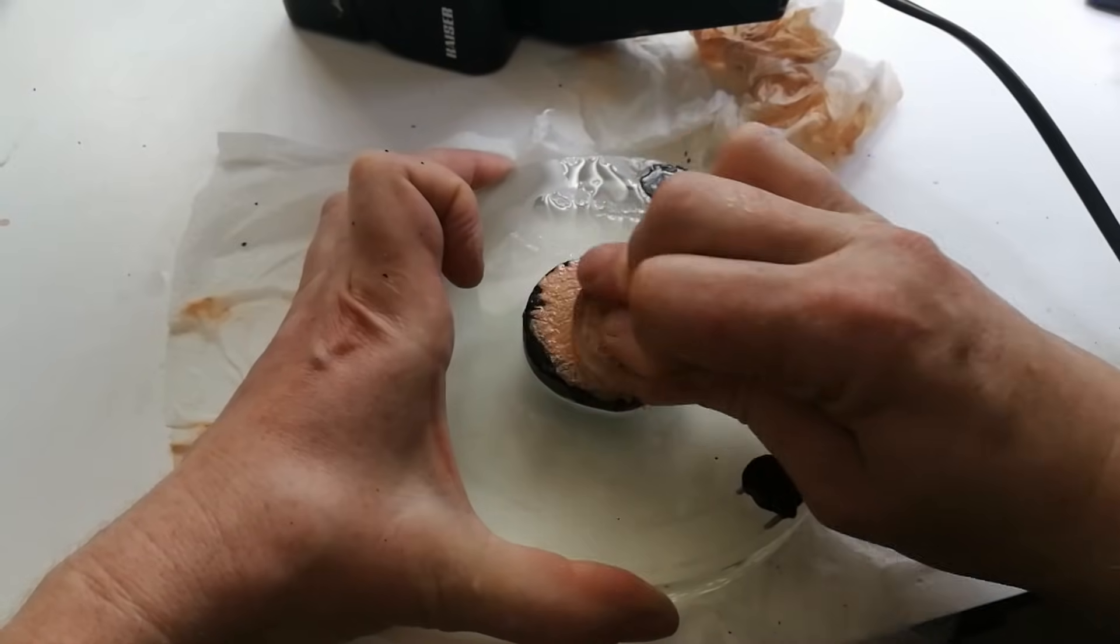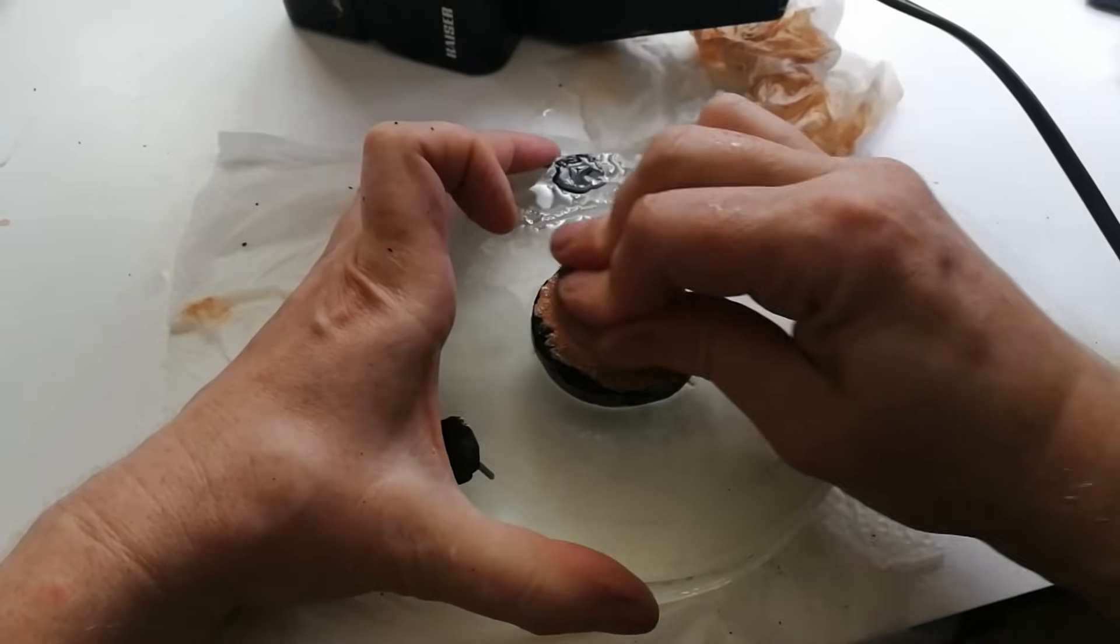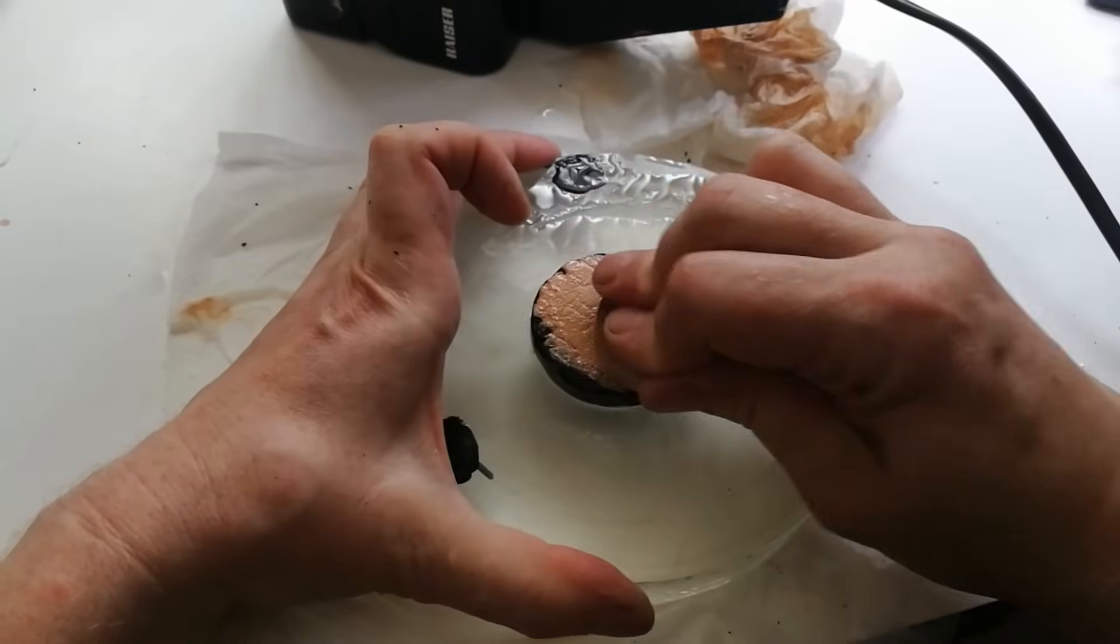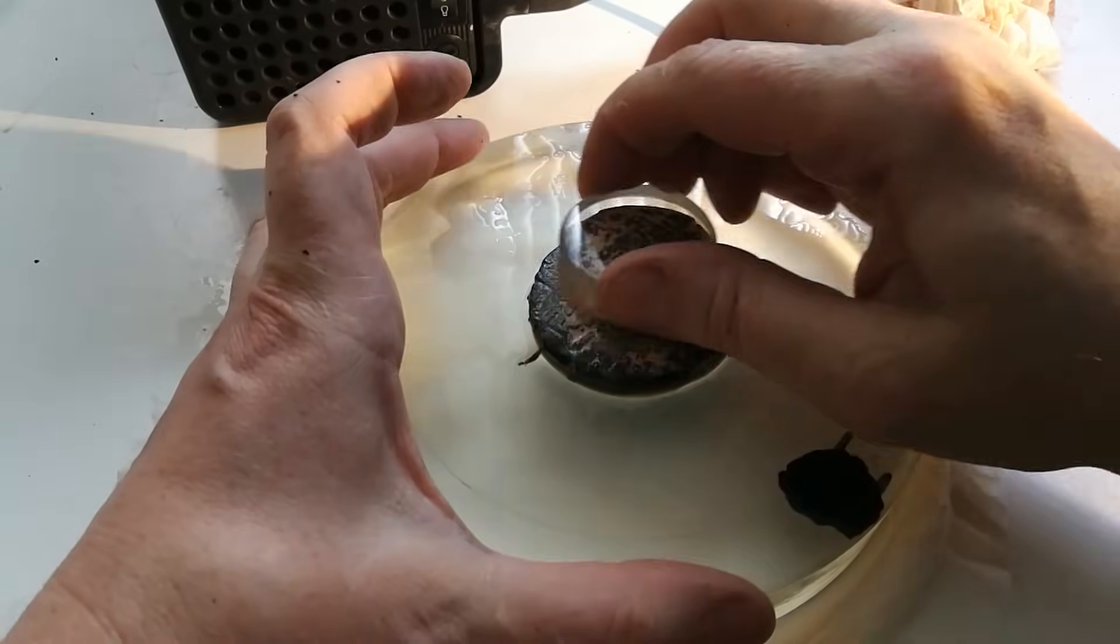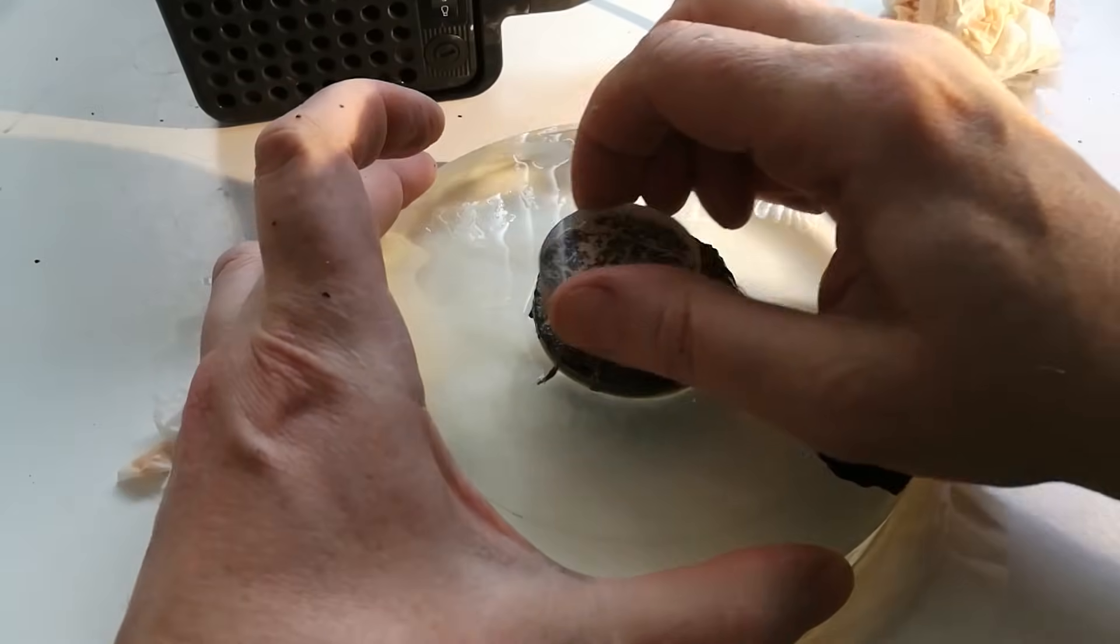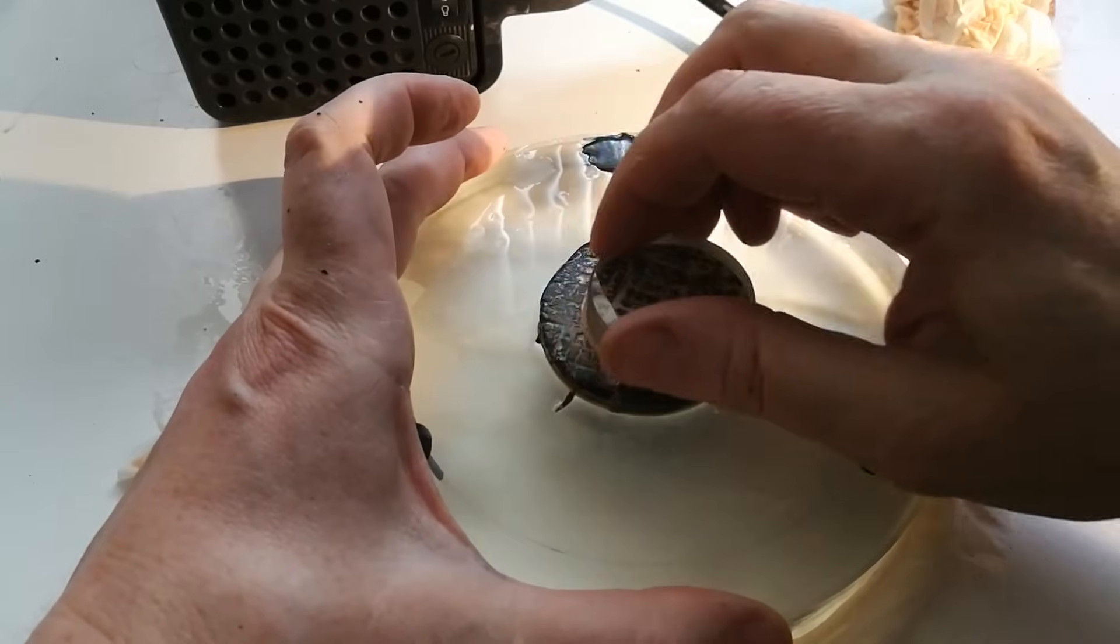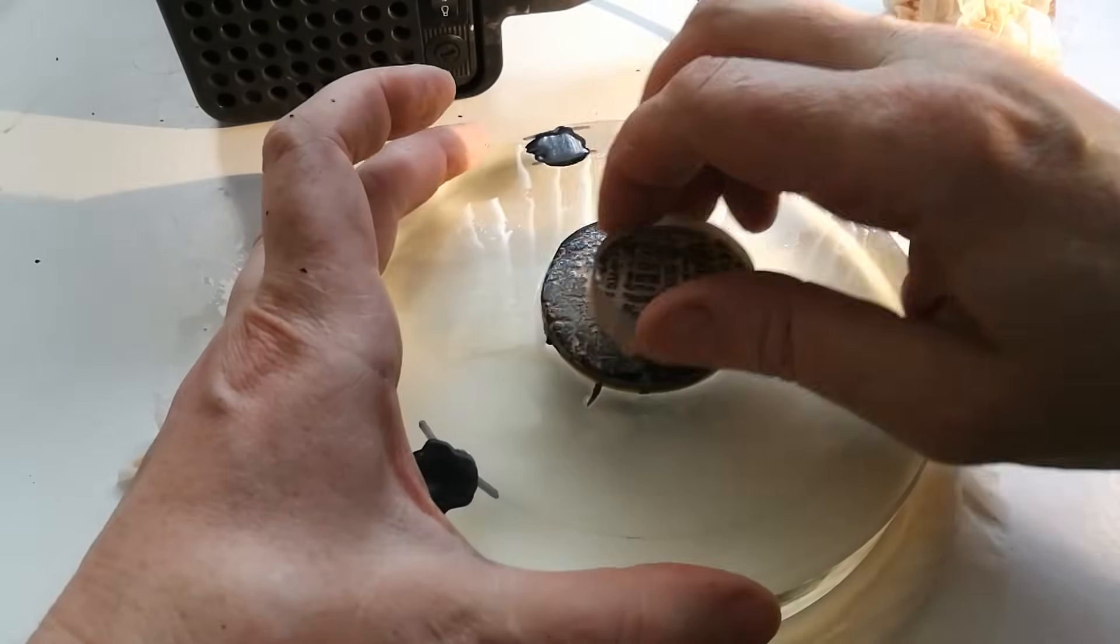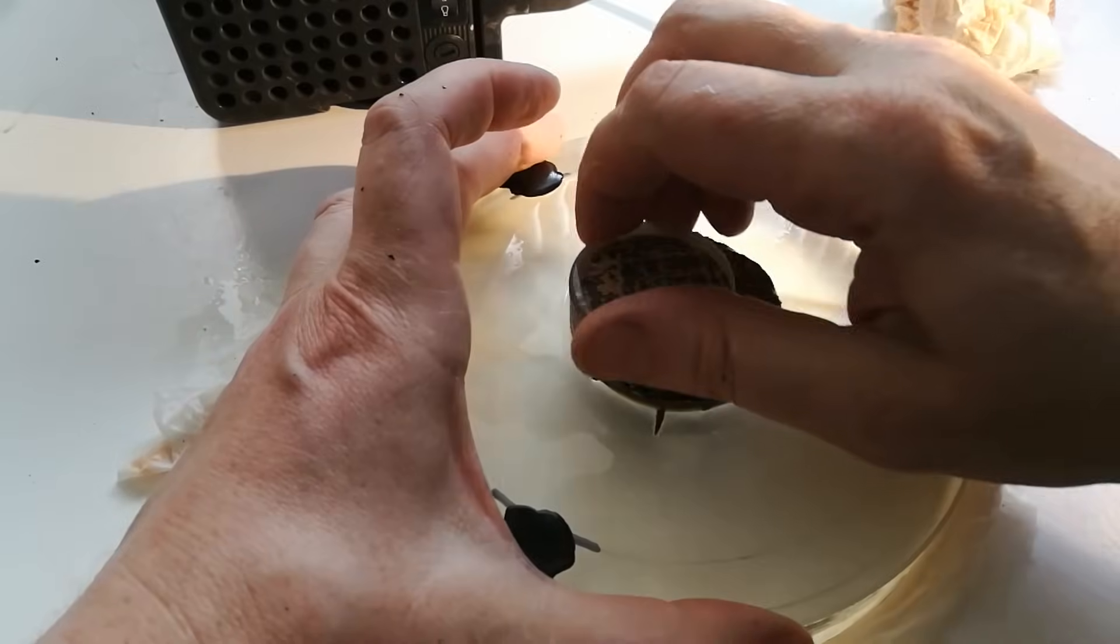The cerium oxide also chemically interacts with the surface, and this process speeds up the removal of glass even further. During polishing we basically use similar strokes as those used in grinding, so short, linear or circular strokes. Polishing however can be quite time consuming since it is a very slow process.